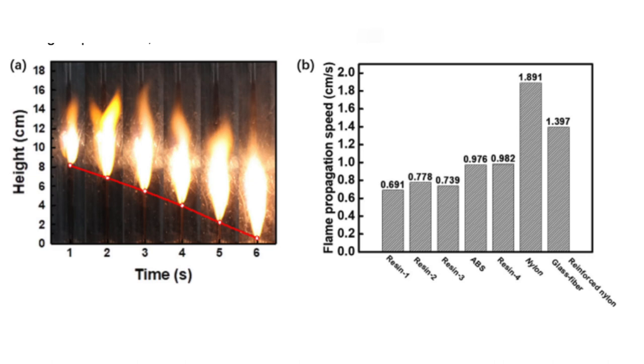The next property of skeletal polymers is their flame propagation speed. To measure this, 3D printed polymeric rods of 2 mm diameter were placed at the center of a cylindrical quartz glass tube. Oxygen gas was supplied into the tube from the bottom through four inlets with ceramic beads as a flow straightener. The rods were ignited at the top and the flame propagated from one end to another. Flame propagation speed is measured by counting the distance between every two instantaneous images divided by the time interval, then averaging the instantaneous speed across adjacent frames.